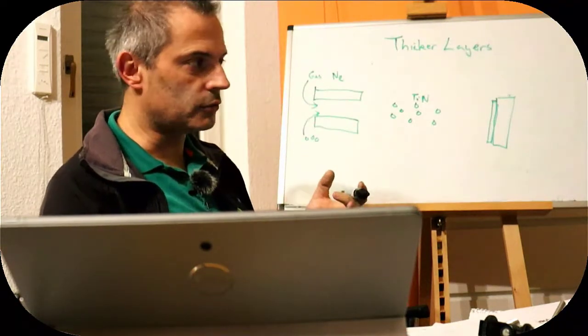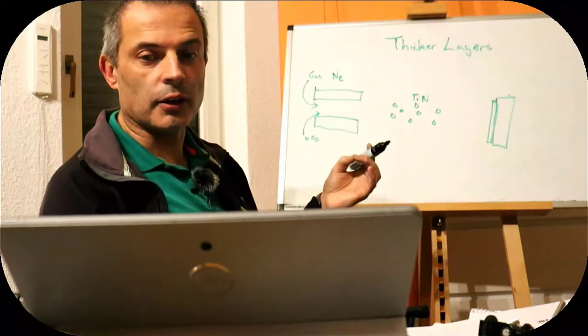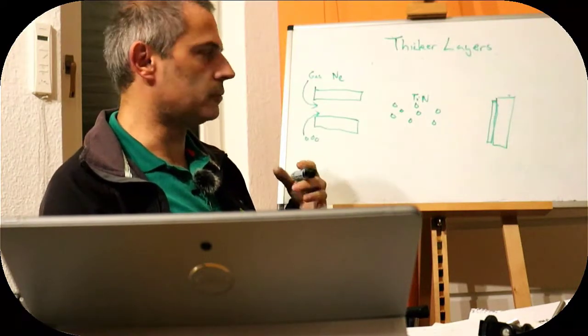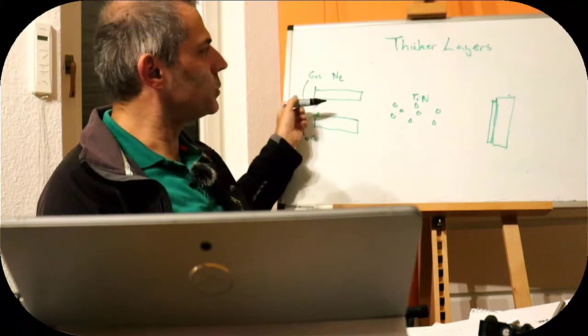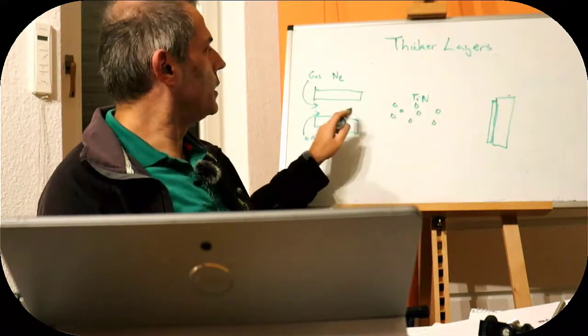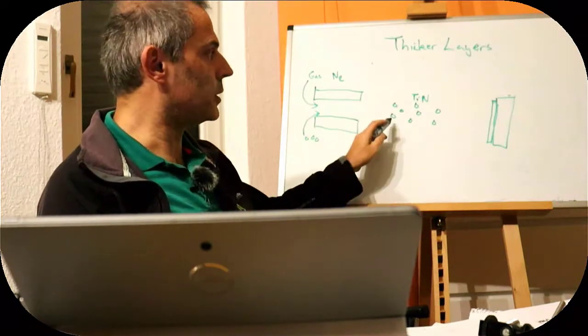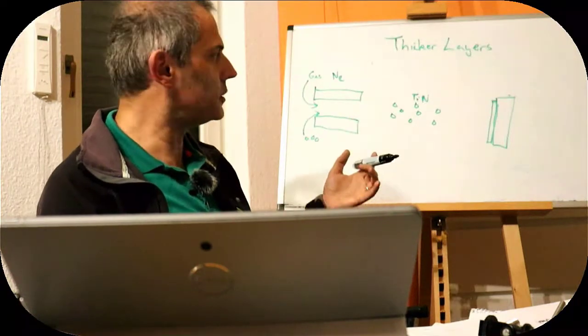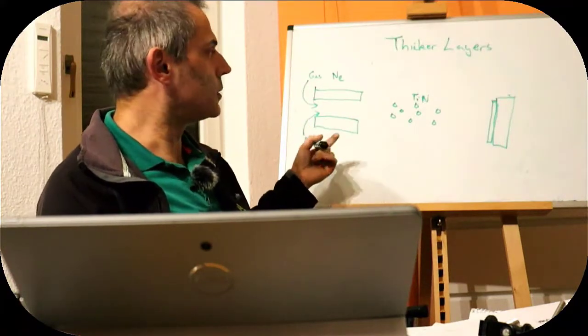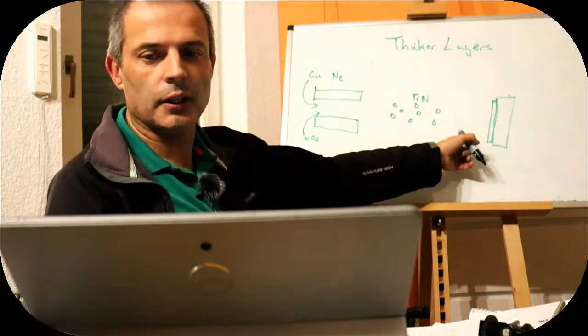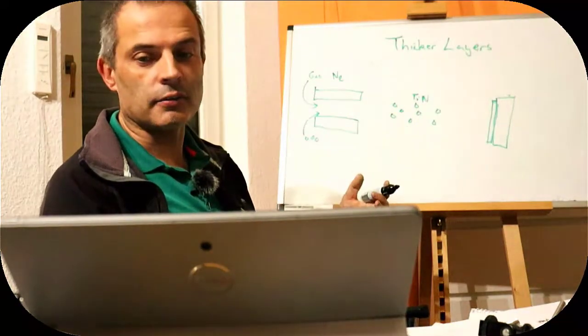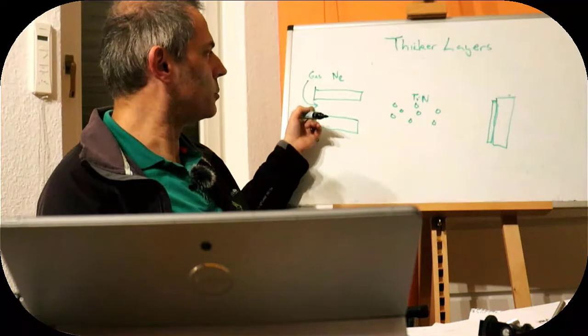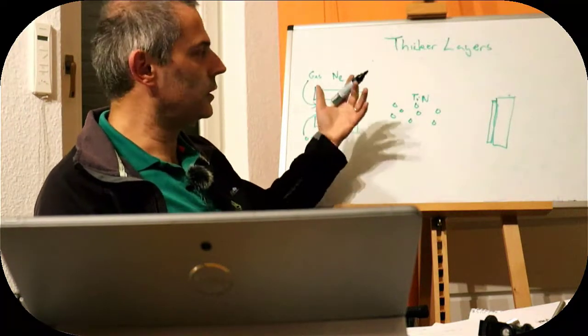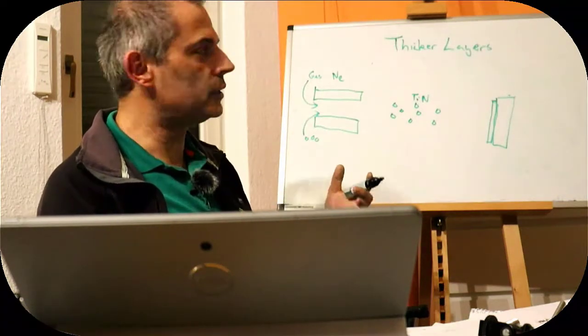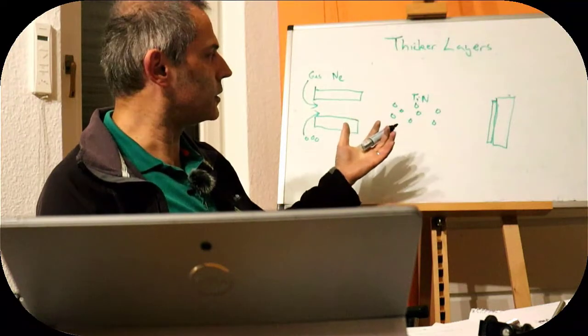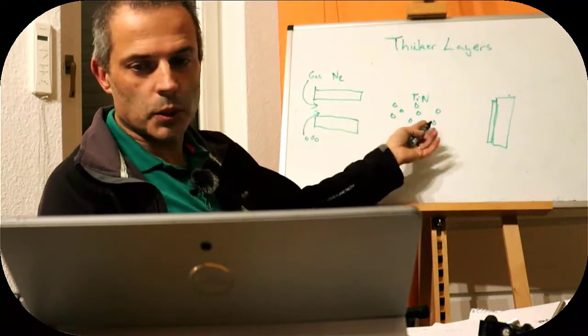Nitrogen has several advantages which get round a new problem that we're going to have. The new problem is, because we're going very, very fast, we don't have very long to heat up our particles. They have to get to about 2000 degrees, and that's tricky, because remember, they're going supersonically, and so we don't have a lot of time. We've got to accelerate them from the base of the gun to the front of the gun to supersonic velocity, so to over 330 meters per second inside our gun,